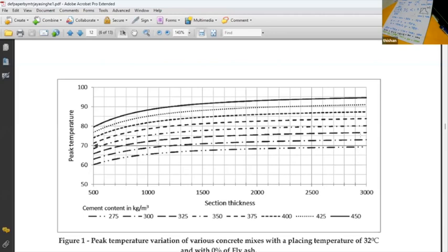But you can see now the temperature is going to be about 73 degrees, 74 degrees. The pour is very large. Temperature is 73, 74. What are you going to do? You are going to reduce the placing temperature. Placing temperature is 32. What we can do is reduce the placing temperature. How are we going to do that? We are going to wet the aggregates the day before, so that water will evaporate by taking all the energy in aggregates. And we'll use 60% water and 40% flaky ice when you are mixing.